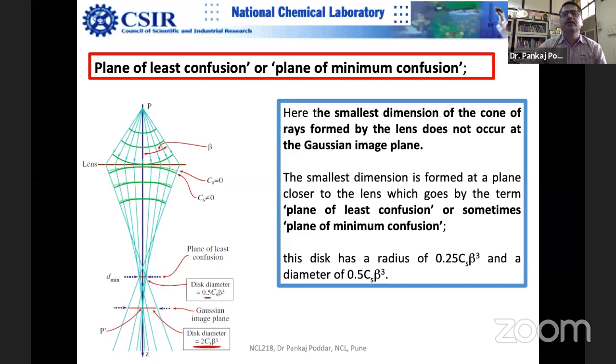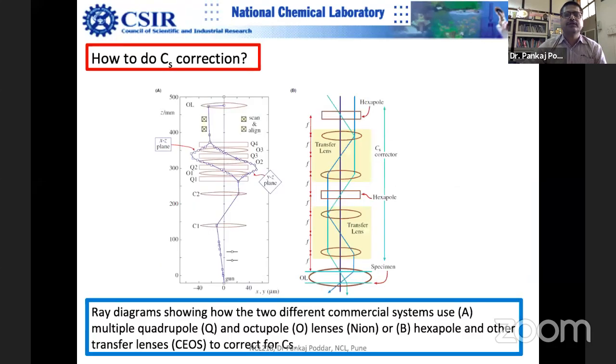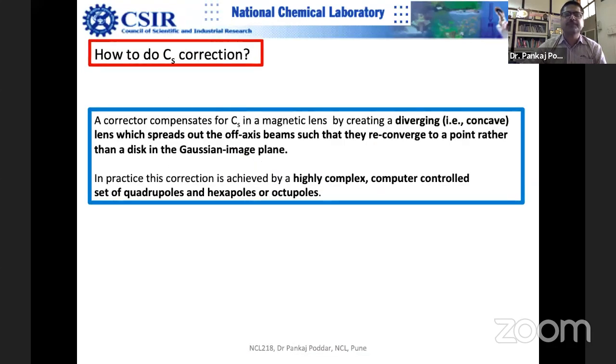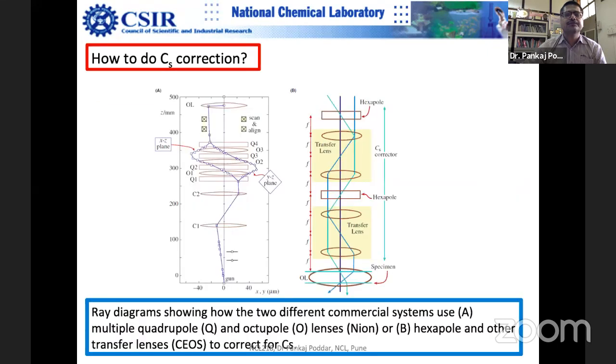Remember that you can't beat the Rayleigh criterion physics on any condition. But there is one more thing which you have to consider seriously before you start worrying about the theoretical limit, which was given by Rayleigh. I'll come to that, and it is very interesting because that has to do with the sample. Your sample also introduces chromatic aberration, and that's why we always say that thumb rule is thinner the better, thinner the better. So that is the final point of today's talk.